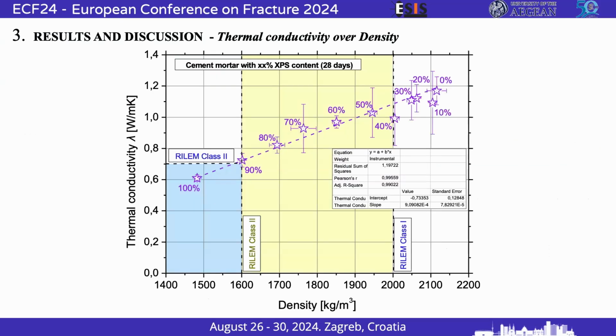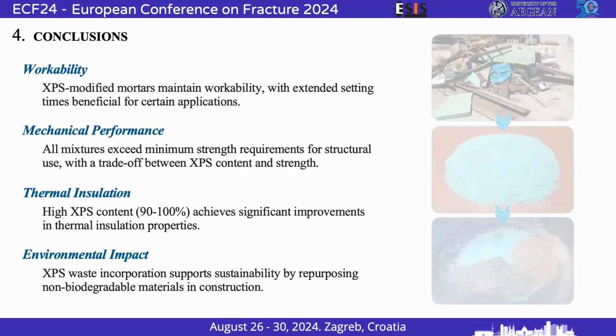And moving on, comparing the thermal conductivity over the density for the different substitution percentages that we have studied, from 0 up to 100%, it was quite interesting that we have seen a linear correlation between the thermal conductivity and the density. And again, here you can see the two different classifications. So this also shows that for percentages higher than 90%, this material is structural, insulating, and lightweight. And for percentages higher than 40%, it can be characterized as a structural and lightweight material.